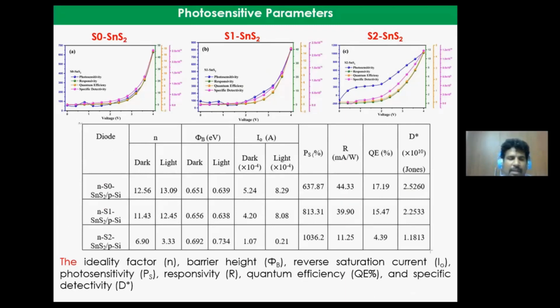As we predicted before, the SnS-based photodiode shows a very high ideality factor, that is 12.56 and 13.09. That is normal because the SnS particle is mixed. There is a huge electronic disturbance between SnS and SnS2. But we got a difference between the structures.